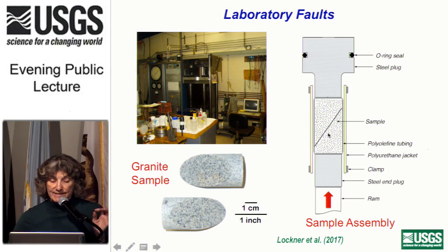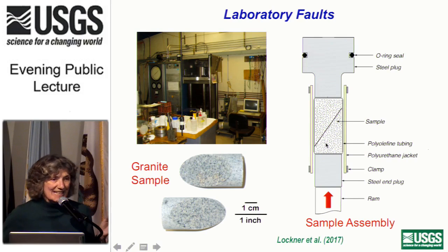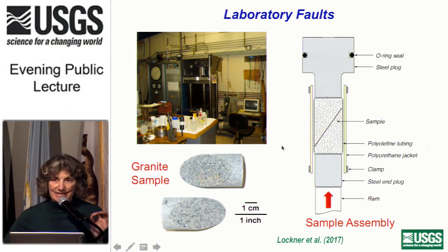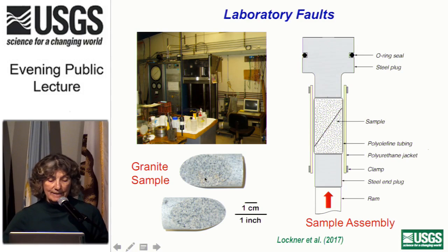But in those events, the frictional heating along the fault plane during those slip events was great enough that we actually melted the granite along the fault. So in the next few slides, I'm going to show you two types of images of the melt textures. And both of them are relatively standard techniques. We'll be looking at backscattered electron images on a vertical slice through the cylinder so that we can see the fault plane here. And then we'll be looking at secondary electron images of the sample that was opened up. So we're looking down on the fault surface at the end.